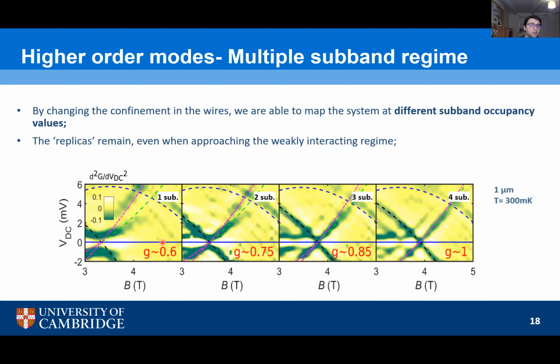Like I said, we can change the confinement in our wires. We can tune the finger up and down, so we can change the density, which allows us to change the interaction strength, but we can also change the number of subbands that are occupied. Everything that I've showed so far was in the single subband regime, but nothing stops us from populating 2, 3, 4 subbands. That's what's done here. This is the same region as shown before, the second level replica, but for multiple subbands. That allows us to change the interaction strength all the way from 0.6 to an essentially non-interacting system.